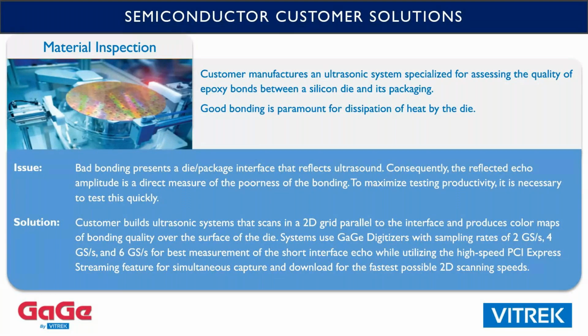So what this customer builds is an ultrasonic inspection system to assess the bonding of the silicon die to its packaging. And the way it does that is, when bonding is really good, the interface between the two components being bonded, in this case the packaging and the silicon die, isn't there, and the sound goes right through the bond. However, if the bond is lousy, if the glue isn't sticking, or if there's some sort of delamination, this presents a reflective interface for ultrasound.